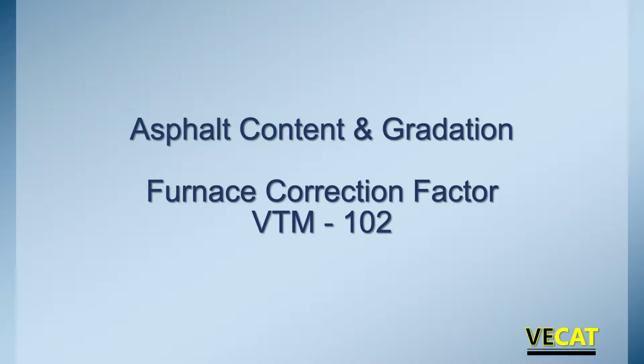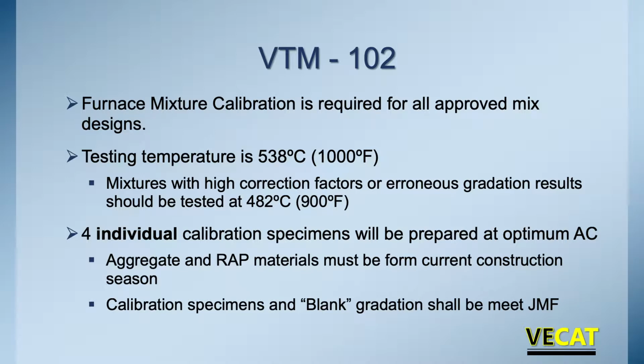This procedure, we follow VTM 102. The furnace mixture calibration is a required part of the approval process for all mix designs in VDOT. The testing temperature for this test is 538 degrees Celsius. I think the majority of the state does use that temperature.